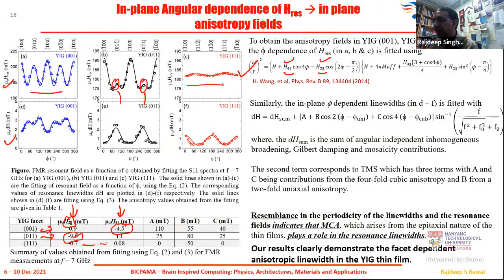And similarly the curve for the ΔH can be fitted using this equation where we have these constants A and C, which are related to the cubic anisotropy, and the constant B is with respect to the uniaxial anisotropy. If you analyze this table, it confirms what is shown by the other results. So what we can say is that there is a resemblance in the periodicity of the line width and the resonant fields, which indicates the magnetocrystalline anisotropy, which appears from the crystalline nature of these epitaxial thin films. They play a very major role in controlling the two magnon scattering, or basically the resonant line width values in this case. So these results clearly demonstrate the facet dependent anisotropic linewidth variation in YIG thin films.